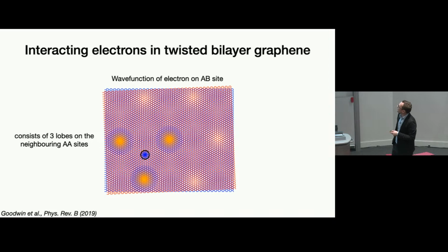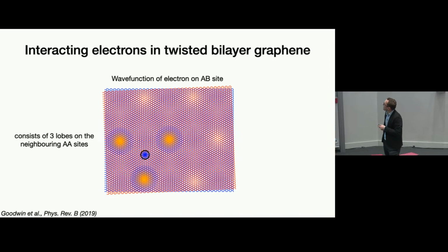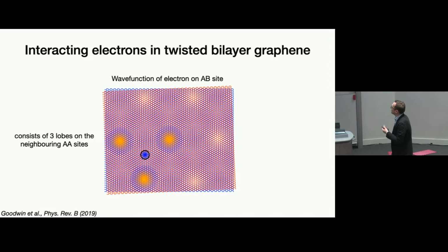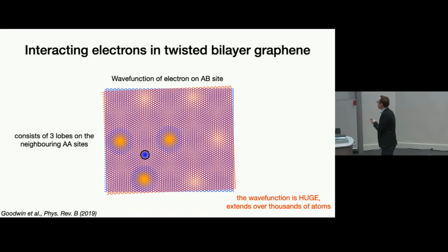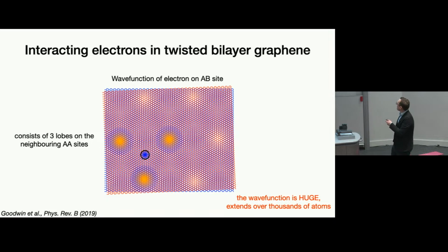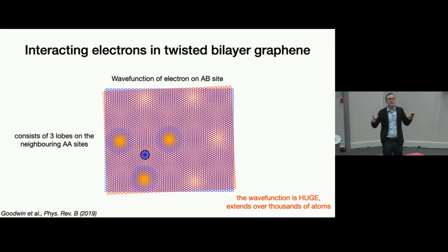What is very interesting is that an electron on the AB site has a wave function that consists of 3 lobes, and these lobes actually sit on the neighboring AA sites. So the electron is actually never on the AB site. The other important observation was that this wave function is huge. Actually, at the magic angle, it extends over thousands of atoms.